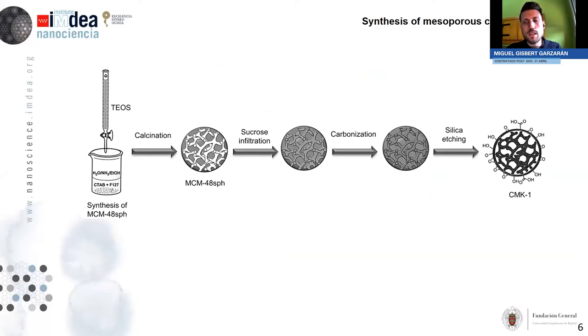Okay, so regarding carbon nanoparticles, the synthesis is quite similar in the sense that we have to synthesize first mesoporous silica nanoparticles. And then we will use those nanoparticles to infiltrate them with an organic precursor. For instance, in this case, we can use sucrose. So then the organic precursor is carbonized. And finally, the silica backbone is removed. So in the end, we end up with carbon nanoparticles, which can be expressed as the negative of the silica template, meaning that where there was a pore in the silica, there will be wall in the carbon nanoparticles, and where there was wall, there will be a pore.